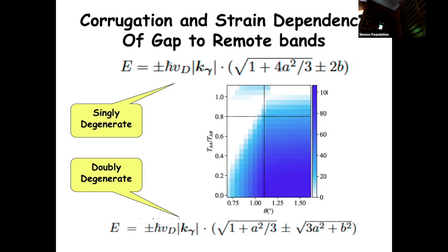When the bands get narrow at this magic twist angle around 1 degree, they narrow to, let's say, 5 millielectron volts. So they're narrow by a factor of, let's say, almost 100. So what's left over after they get narrow depends on a lot of details. And so, for example, this is one detail that was left out in our original work on this. And that is,